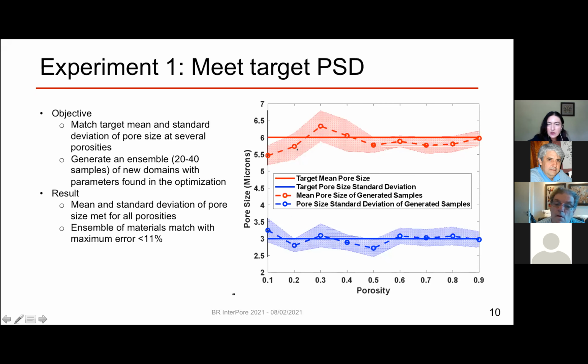And this is basically our ensemble calculations. And the dashed line is the average. And you see that we can get to very good agreement, especially at the porosities of 0.3, 0.4 and higher. The ensemble of materials matches with the maximum error that is below 11%. So we're pretty happy with that result. Now, for the mean, the error was about 4% and 5% for standard deviation on average.